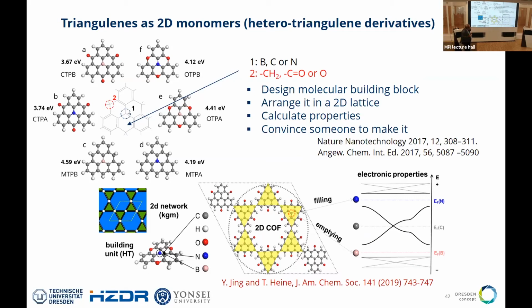So essentially you have the same situation as in a honeycomb lattice, as in graphene. You get a band structure with a Dirac cone; well, that's just a scheme here. I will show you afterwards that the scheme is very close to reality. We have a Dirac cone here, right? And this Dirac point is at the Fermi level, and you have something like a 7 times magnified graphene. Nothing else. Great. So now you replace the carbon by boron.